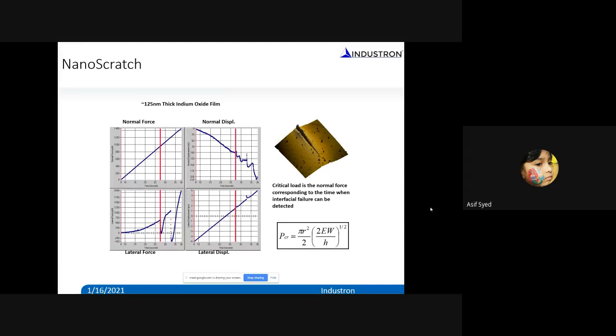And from the normal force and the lateral force, you can calculate the coefficient of friction. And if you do that on a material, for example, if you have a thin film coating on a substrate, and you want to measure the adhesion strength of this coating, you can use this kind of technique where you progressively increase the normal load. At some point, the material will delaminate from the surface, and you can measure the critical load required to delaminate the material. From this equation, you can measure the adhesion strength between this coating and the substrate.